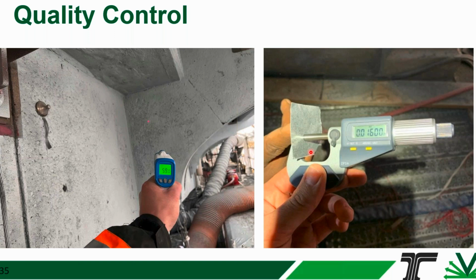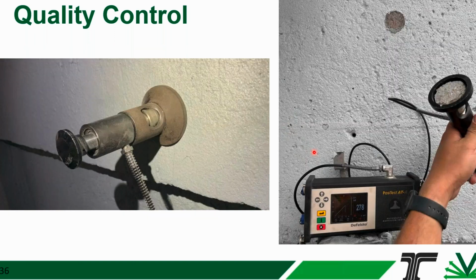And so on the left, we have basically a pull-off test device. On the right, you can see the pull-off test device after the pull-off is complete. You can see the layer of zinc on the dolly, and you've pulled the zinc off of the surface of the concrete, and you're going to measure the pull-off strength in PSI. Normally, most specifications are going to say around 150 PSI or greater, or something in that range. That's 278. This is from another test, 268. So both of those are good.